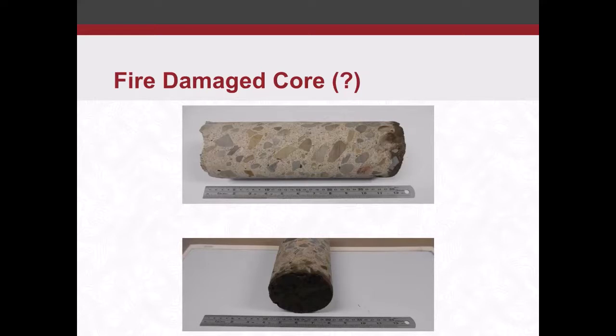Fire damaged concrete typically, if anybody's seen it or read about it, looks kind of pink colored, peach colored. And the surface is definitely softer. You could probably scratch it away with a metal tool. But the core we're looking at here on the screen, I brought this because we did take some cores and we did do some compressive strength. We didn't know what the original design strength was.